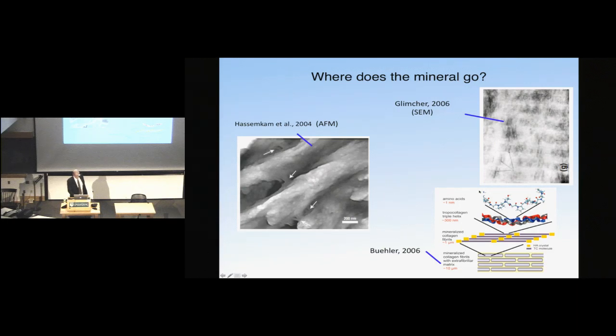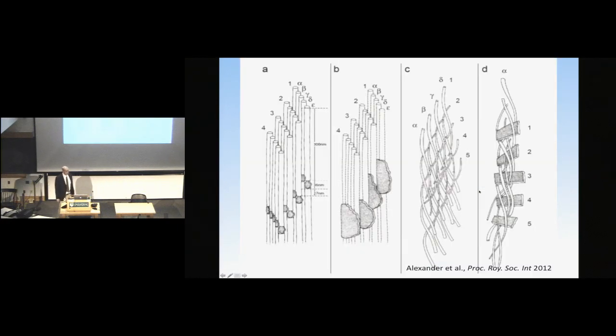So then we underwent a very long process. We actually spent about 5 years trying to sort out this issue, and we dug back in the literature and found a series of old models which really treat bone collagen as a pipe organ with little bits of mineral in between staggerings that are observed nanoscopically. But this ended up not providing enough mineral to account for everything in bone. There were some later models that said perhaps there are plates of mineral between the tropocollagen molecules, but this isn't possible because of Orgel's structure, which we idealize as this twisted structure here.